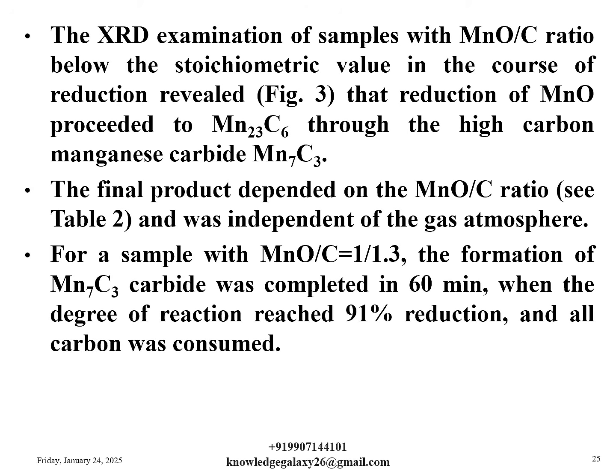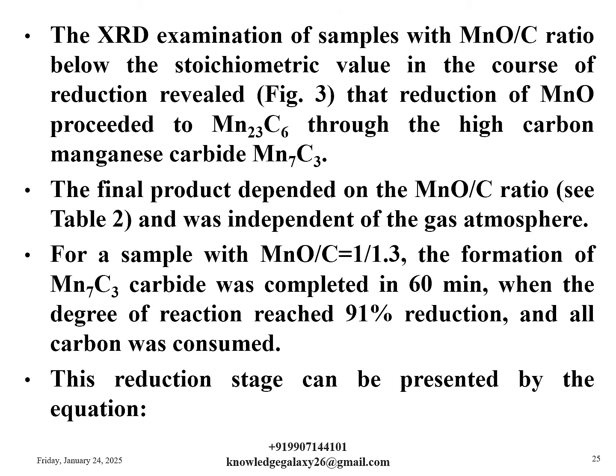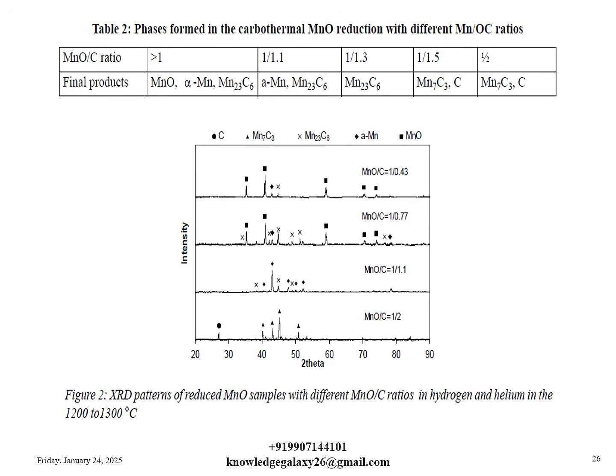For a sample with MnO by C ratio equal to 1 by 1.3, the formation of Mn7C3 carbide was completed in 60 minutes when the degree of reaction reached 91% reduction and all carbon was consumed. This reduction stage can be presented by the equation. So this is the table 2 which I have just explained. Table 2 shows the phases formed in the carbothermal MnO reduction with different MnO by C ratios.